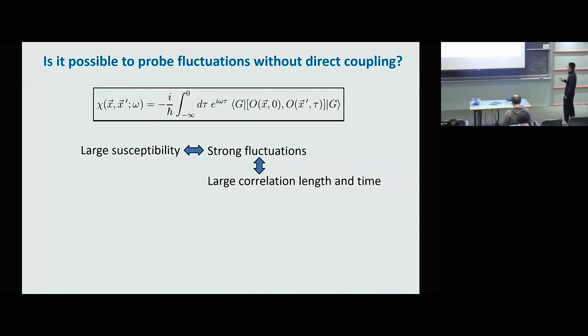So there's an interesting implication here. Of course, large correlation length and time are also connected because if the correlation length is large, then a large region of the system has to fluctuate together, so it cannot be very fast, it has to be slow. So this tells us that, in principle, we can try to probe some important properties of the fluctuations from the time domain, because a strong fluctuation will intrinsically give rise to slow dynamics. Of course, I'm using a single arrow here because there are many other reasons which can give us slow dynamics, like delivery of pizza can also be slow. So we have to be very careful here.